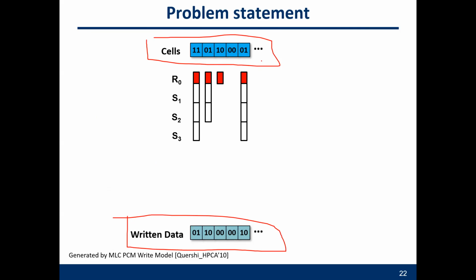Again, we write different contents. We need to generate a different amount of crystalline filaments in the amorphous fraction. If the growth path of your crystalline filaments has more antimony, then basically you are faster. This write operation can be faster. You use fewer iterations of writes, then you can finish earlier. And for some unlucky cell, it has very little antimony, then it will take a longer time to finish the write.